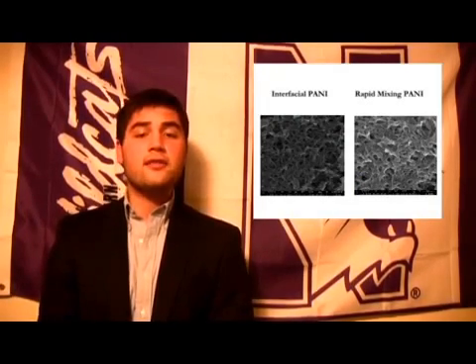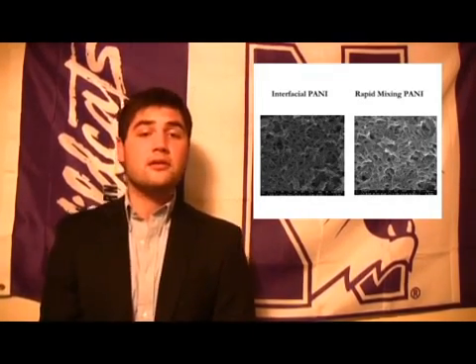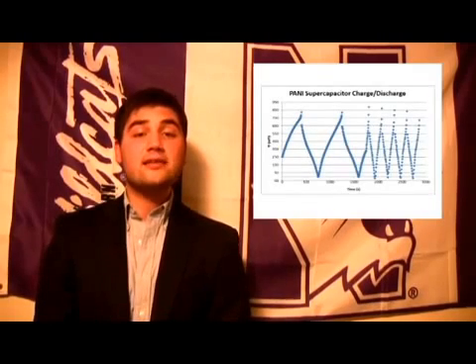On both samples, use dialysis to purify the nanofibers — and voilà! We've made a conductive polymer out of nothing more than common lab ingredients and a monomer solution. How about if polyaniline nanofibers could be used as a supercapacitor? In Northwestern University's battery lab, polyaniline was deposited on two metal substrates, separated by a porous membrane soaked in sulfuric acid, and pressed into a conventional coin cell. By connecting the capacitor to a 200 to 600 microamp power source and measuring the voltage drop across the coin cell, we can see a clear charge-discharge behavior, indicative of a capacitor.